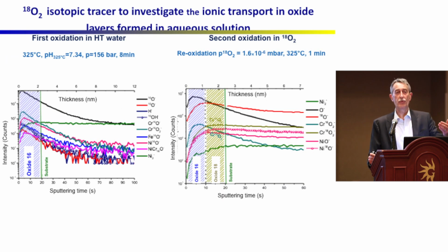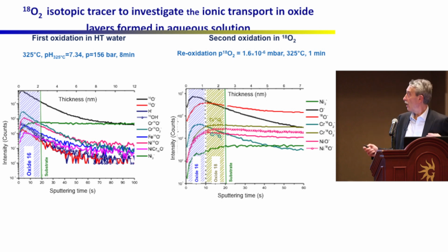The way we do it is, again, a two-step experiment. But now we do the first oxidation in water at high temperature. This is done in an autoclave in collaboration with EDF. Then we look at the oxide formed by XPS, time-of-flight SIMS, STM, or whatever. But then in the time-of-flight SIMS, we can re-oxidize the oxide using oxygen-18 and look at where the oxide is forming at the beginning. So we did that, and these are profiles after the first oxidation in water at high temperature, for short times. This is a special autoclave that allows us to do short-time experiments in high temperature water.